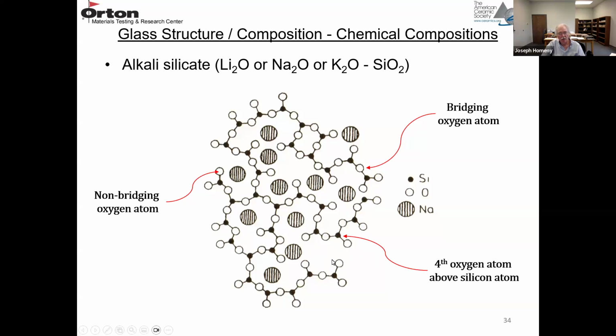And again, this will have a big effect on viscosity, which is one of the important properties of a glass in a refractory. If you're going to have a glass present, you want to have a viscous glass. You don't want to have a fluid glass at high temperatures. And there are refractories like AZS that you deliberately put in a silicate glass, but you put in a very viscous silicate glass.